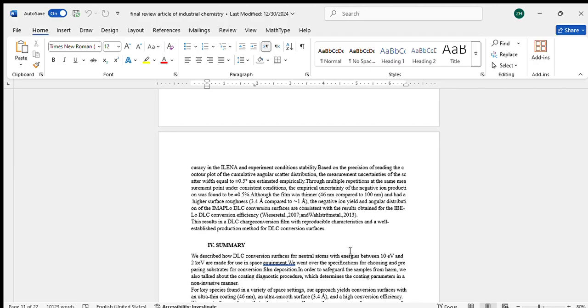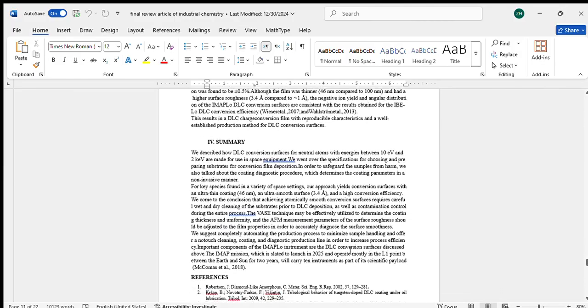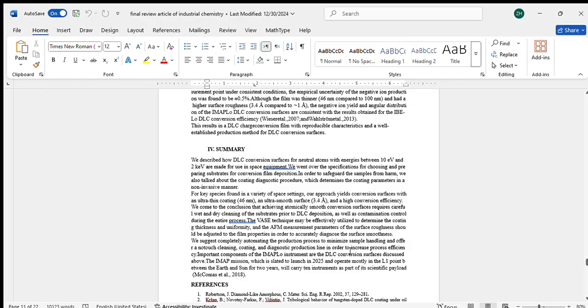And the conclusions: overall, the IMAP-Lo DLC conversion surfaces demonstrated reproducible performance with consistent conversion efficiency and angular scatter characteristics. The improvements in film thickness and surface smoothness were essential in achieving these outcomes. So now we will see here the summary of this article. The key points are about the DLC conversion surfaces and their preparation, coatings, and testing for use in the IMAP mission.